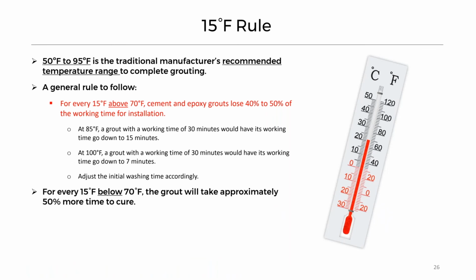There is a 15-degree rule out there if you do any hot weather grouting, or for the home builder market, we deal with that market a lot. The traditional manufacturer's recommended range of temperature for grouting is 50 to 95 F. For every 15 degrees above 70, cement grouts for sure, epoxy is a little bit less than that, lose at least 40 to 50% of the working time. So as a good example, the 85-degree bullet there: if your working time is 30 minutes at 85 degrees, that's going to go down to 15 minutes.